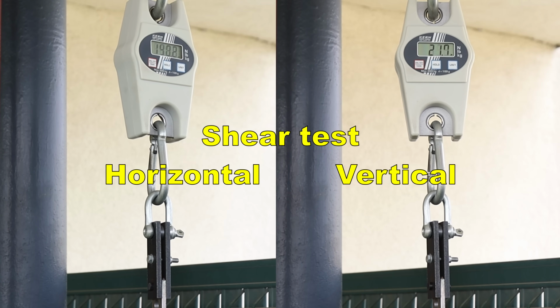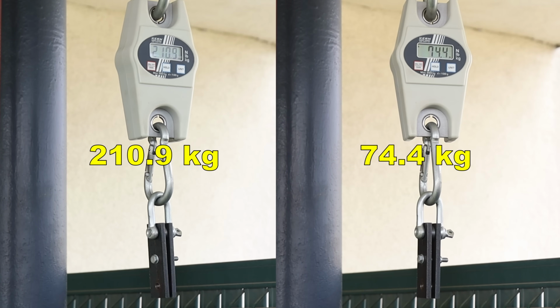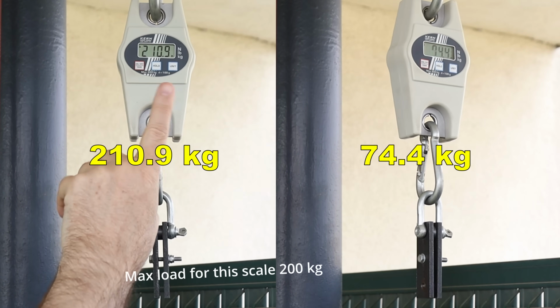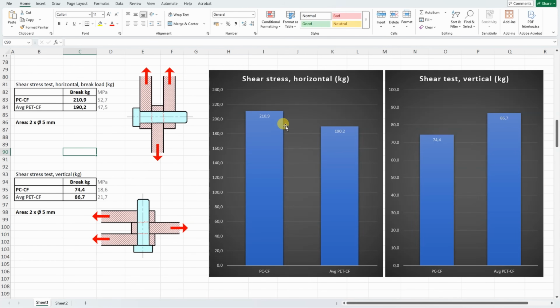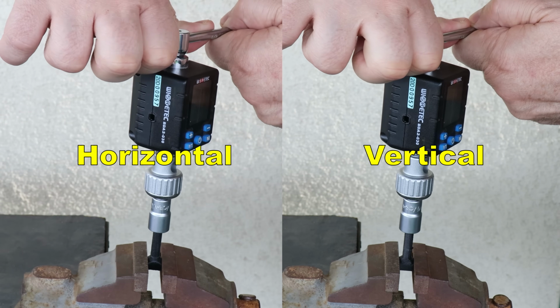Shear test side by side, horizontal and vertical. With horizontal just a little bit over the max load. In horizontal position a little bit stronger compared to the average PET-CF, printed in vertical position a little bit weaker, but more or less they are very close to each other. Torsion test, horizontal and vertical.